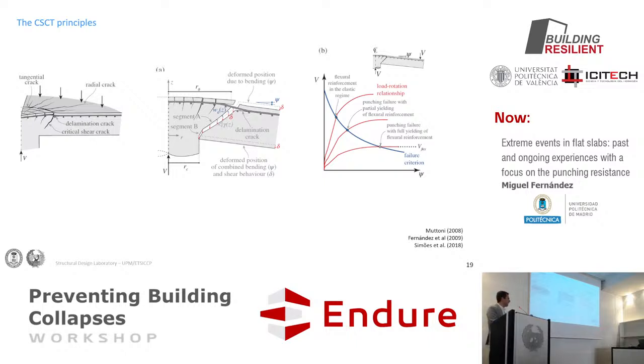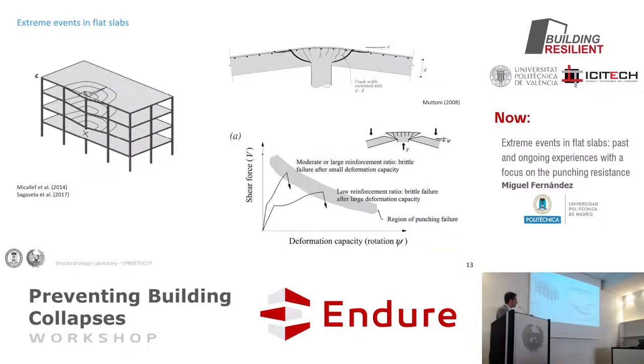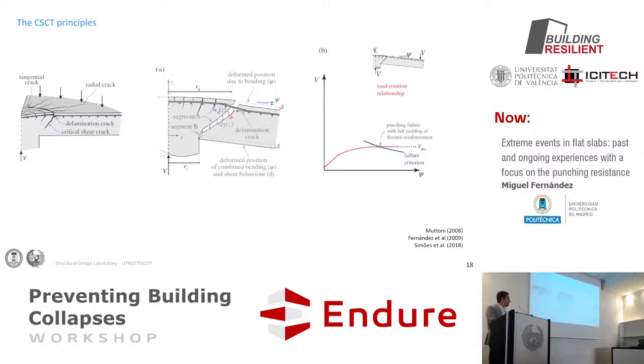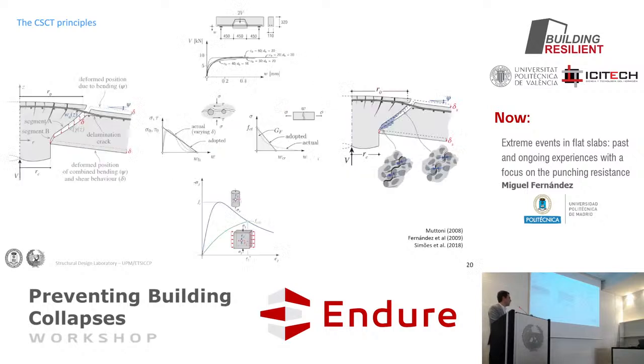And so we have a failure associated. So all these points here define this failure region that we were describing, this region of punching failure. They are more or less connected in this manner. So the lower the deformation, let's say psi as a parameter to measure that, the lower the opening of the cracks, the higher the capacity we can engage through the two surfaces. The more the cracks open, the lower the shear resisting actions that transfer shear.